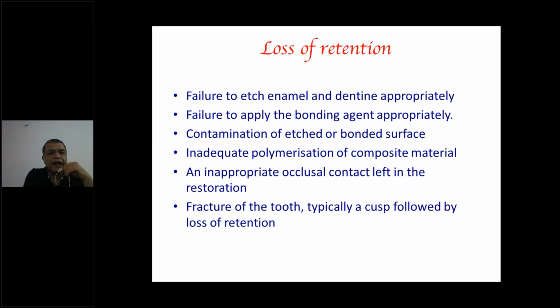The loss of retention can happen if you have failed to etch enamel and dentine appropriately, or you have failed to apply the bonding agent appropriately. Contamination of etched and bonded surfaces, as I told you, can lead to the failure of adhesion of composite and tooth structure. If you have inadequately polymerized the composite material, that can also lead to loss of retention. And please always check if there are any inappropriate occlusal contacts left in the restoration.